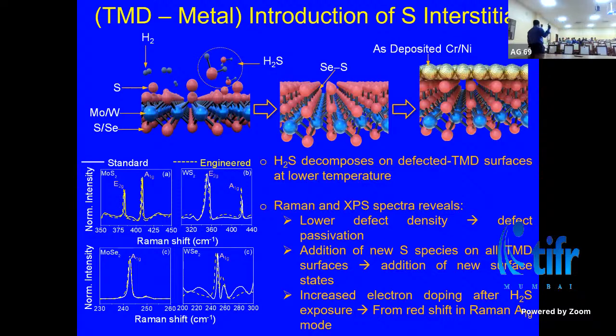So you can actually do this process inside the same CVD chamber inside which you might be growing these TMDs, right? So first you grow it at different temperatures, and then you bring it back, and under certain optimum H2S flow rate and temperature conditions, they decompose on the surface, and when they decompose, they leave sulfur and the hydrogen. Right? So now the sulfur stays on the surface, it actually goes and sticks into the interstitial site, and then you can bring metal on top of it and you can make a contact. Now this is more stable because you can do all kinds of process steps afterwards, and the interstitial doping that you're doing does not go anywhere else, right? It stays packed under the metal part, right?